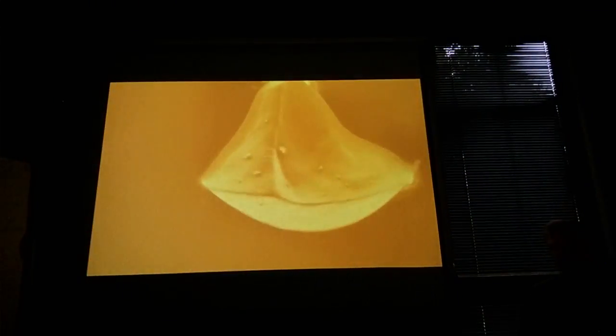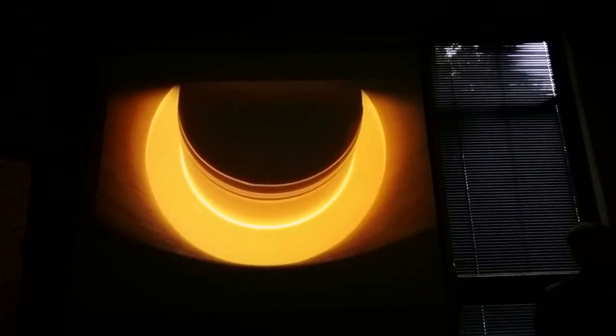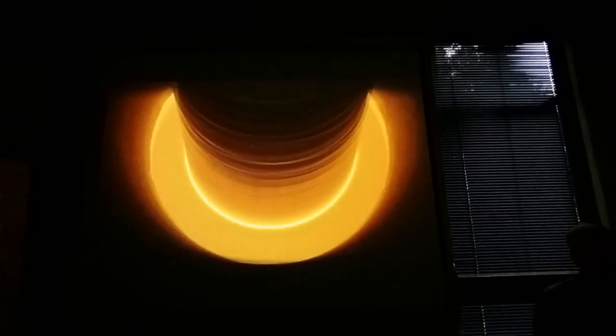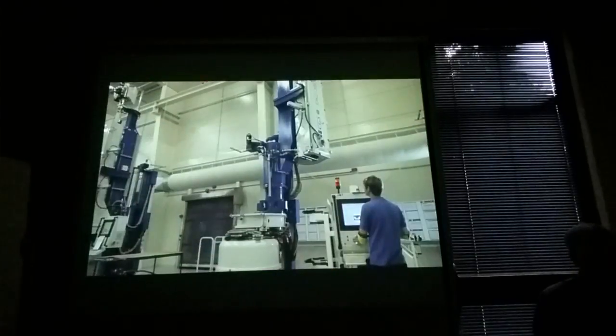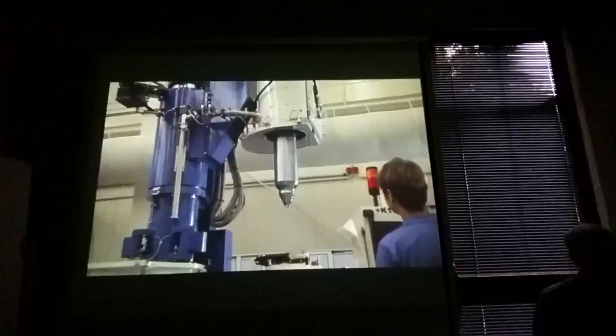Raw silicon is melted at temperatures of over 1,400 degrees centigrade. A thin rod, known as the seed crystal, is then submerged into the liquid raw silicon and pulled back up very slowly. At this step in the process, the liquid silicon accumulates on the seed crystal and solidifies. Over 4 days, a silicon rod of up to 2.8 meters length takes shape.